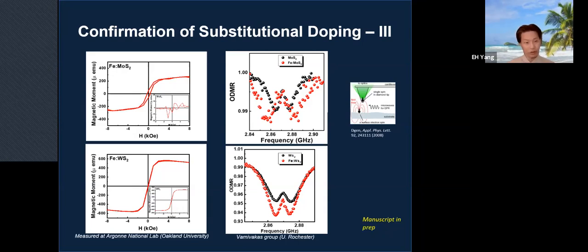On the bottom left is the SQUID result of iron-doped tungsten disulfide, and this is called paramagnetic. So it works under a magnetic field, but when you remove the field, that's gone, right? On the other hand, the iron-doped molybdenum disulfide SQUID result, top left, shows ferromagnetic behavior with coercivity, right? At the center, you have this hysteresis loop, right?